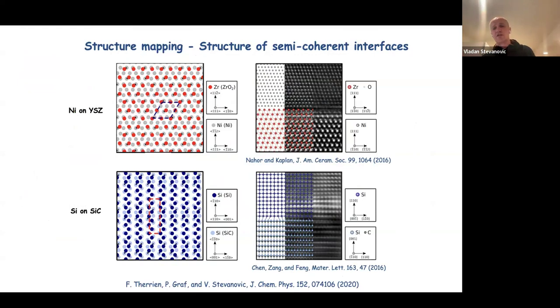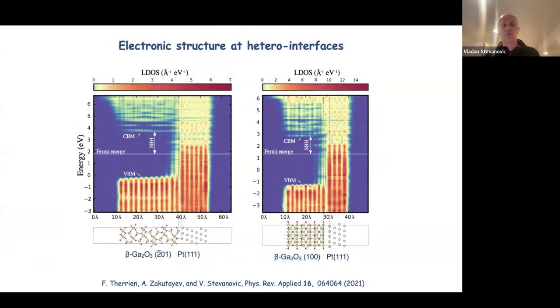Just want to say in really 2 sentences, you can adapt our structure matching procedure for phase transitions into a structure matching procedure for 2D structures, and then do some interface modeling. It seems promising. We are able to reproduce these TEM images for nickel on yttrium stabilized zirconia, silicon grown on silicon carbide. You can then use this to predict Schottky barriers, let's say between gallium oxide and platinum.